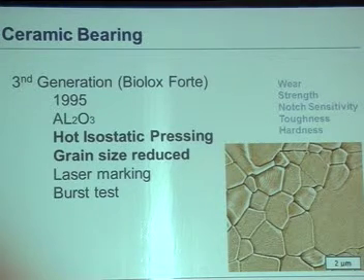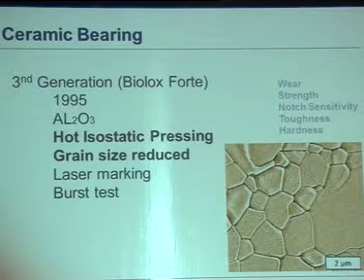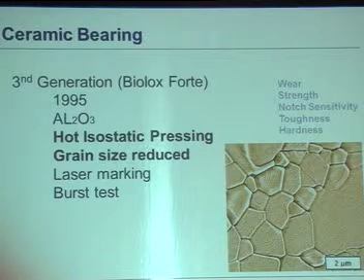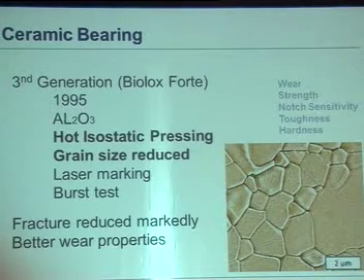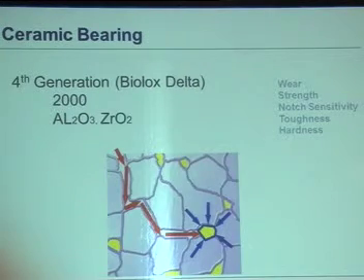They also realized that ceramic has a notch sensitivity problem, so they changed to laser marking. The quality control also improved. They would do a burst test of all ceramic heads, and those that survived would be released in the market. But still, fractures were seen, though not as many as before. So then the zirconia part came. Alumina has some definitely better properties of ceramic, whereas zirconia has some other advantages. So combined together in the fourth generation, it's amazing the way the engineers did it.